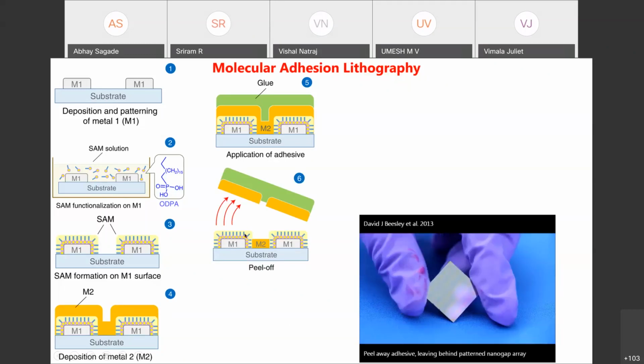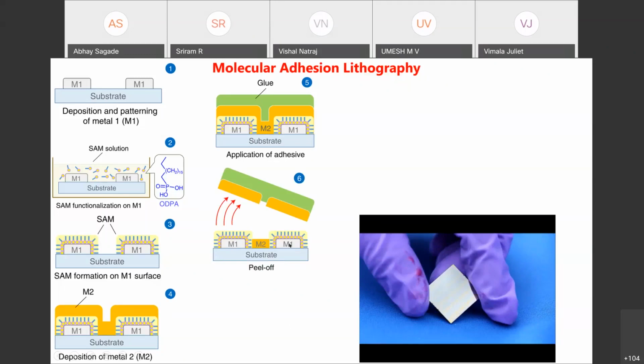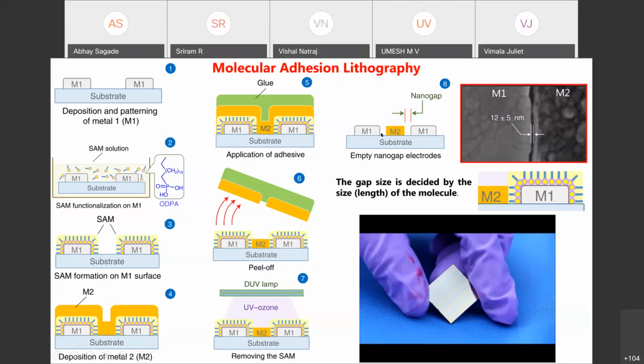But only the regions which are coated on top of the SAM molecule get lifted off. And that's why, as you can see in this video, metal 1 stays there and metal 2 is separated from metal 1 by a distance which is almost equal to the length of a molecule. And at the last step, you expose this whole substrate to UV light with ozone, and it will burn away all this organic SAM molecule. And you will end up with a substrate with metal 1 separated by a distance equal to the length of a molecule, and then metal 2.